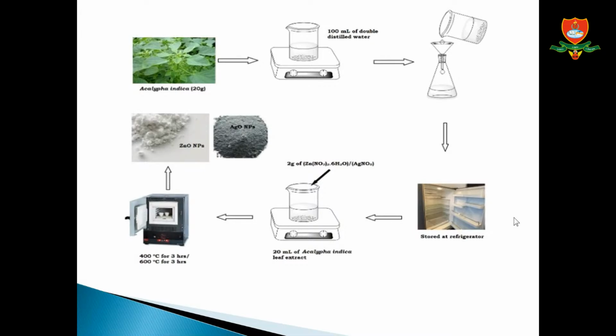was formed. It was cooled at room temperature, and then the colored extract was filtered using filter paper and placed in a refrigerator. Take the Acalypha indica leaf extract from the solution and boil at 60 to 80 degrees Celsius. When the temperature reached 60 degrees Celsius, 2 grams each of zinc nitrate and silver nitrate were added. The mixture was boiled until it formed a golden brown colored paste.